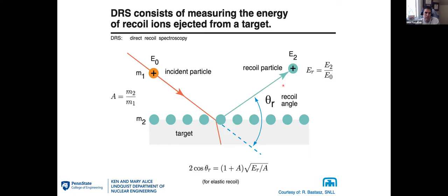The other technique we use is called direct recoil spectroscopy, which is very similar, but instead of the incident particle backscattering and being detected, we are detecting the recoil particles. So these would be the actual target atoms that are recoiled and emitted into our detector as ions. Again, those tend to be a very, very small percentage of the actual recoiled particles that we're capturing.